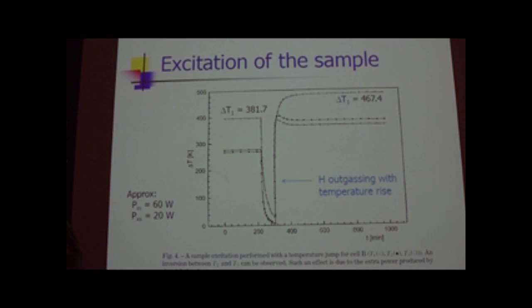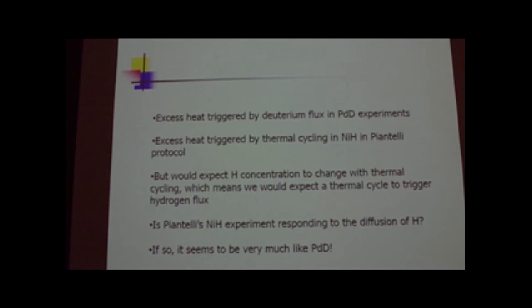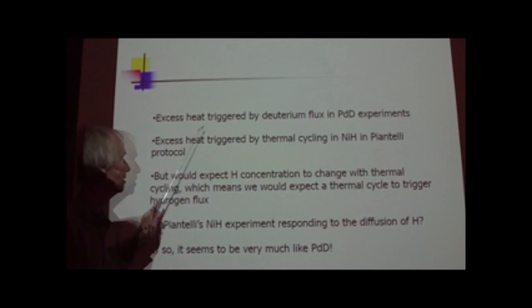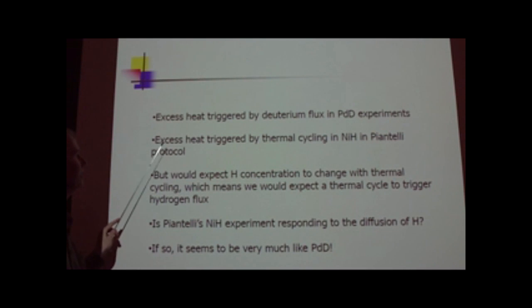In nickel hydrogen, the temperature cycling is inducing a hydrogen flux, which is kicking on the excess heat. Now in this case, it's not causing optical phonon excitation because we don't have much in the way of optical phonon modes. They're delocalized. So that probably isn't important here. On the other hand, we can also cause high-frequency acoustical mode excitation as a result of the diffusion. So excess heat is triggered by deuterium flux in palladium deuteride, and by this interpretation, excess heat is being produced by a hydrogen flux in nickel hydride produced by this thermal cycling.